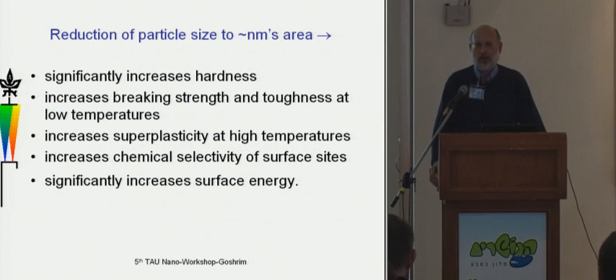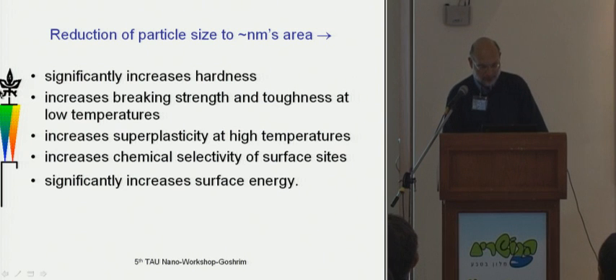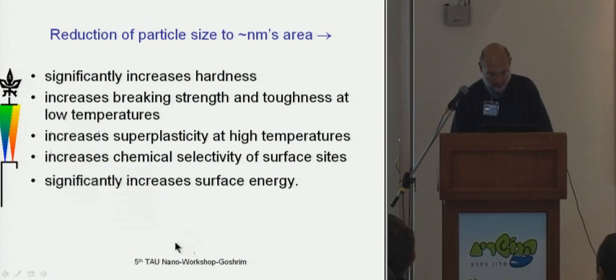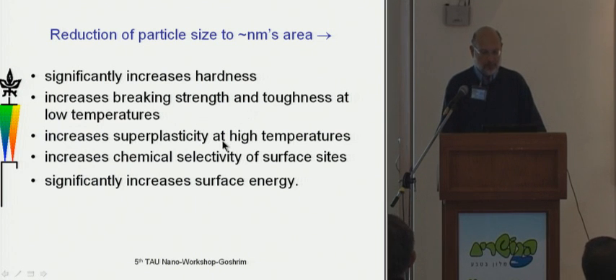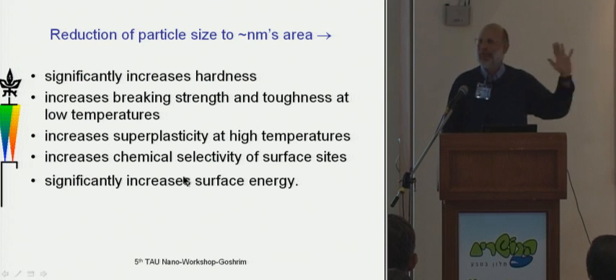In the literature, there's all kinds of talk about what happens when you reduce the size of bulk material to the nanoscale. It can significantly increase hardness. It can increase the strength and toughness of the material, particularly at low temperature. It can increase superplasticity at high temperatures. It can increase chemical selectivity at surface sites and significantly increase surface energy. I take it for granted that all this is true. I haven't checked. My concern is, how do we make the material?